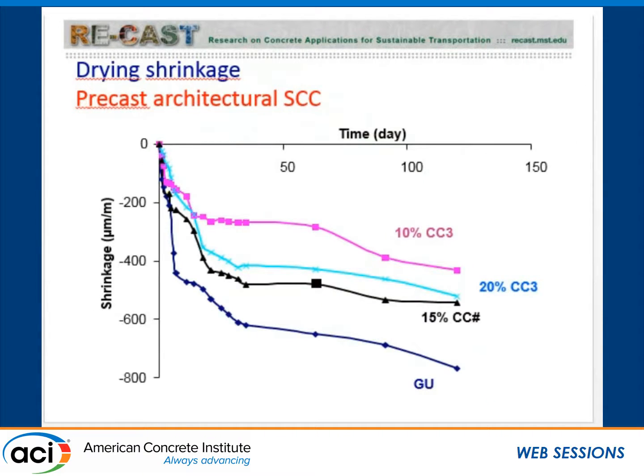So the document 212 proportioning mentions something about shrinkage. This is what we had in terms of shrinkage, and these are drying shrinkage values after 7 days of moist curing. We see here after 7 days of moist curing, followed by about 120 days of drying, the type GU cement has the highest shrinkage, about 700 microstrain, and the use of finely ground limestone filler is reducing it, especially in the case of 10%, and then a little bit less with the other 2. We also looked at autogenous shrinkage and creep, but I'm not mentioning that here. They are in the paper.